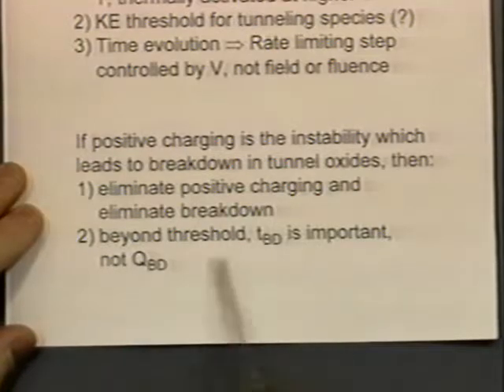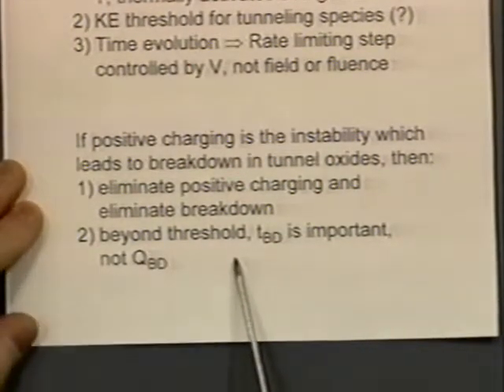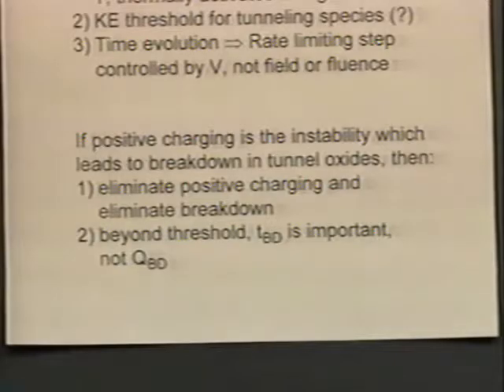And beyond the threshold, let's say you really have to sit above the threshold, how do we predict the lifetime of the device? Now what I say is that you have to watch this time evolution process. I don't have any foils for this, so we have to use our heads here. If you have a thicker oxide, you have a small amount of current passing through for a given time. If you make the oxide a little thinner, you exponentially increase the amount of current that's passing through the device, or the fluence, or the amount of Q, charge, that passes through the device.